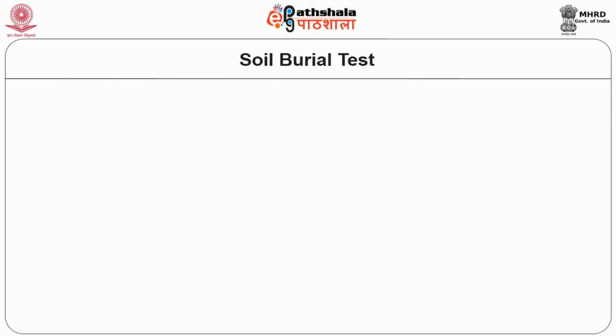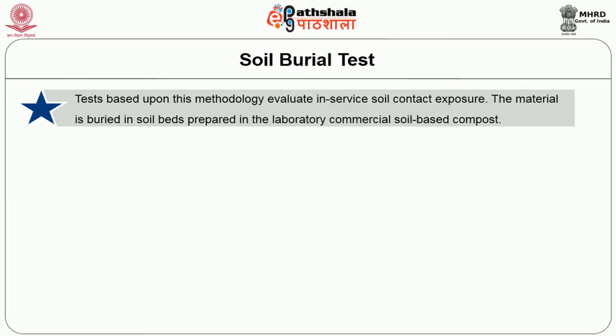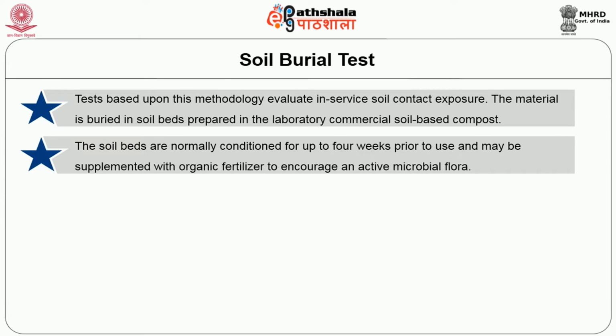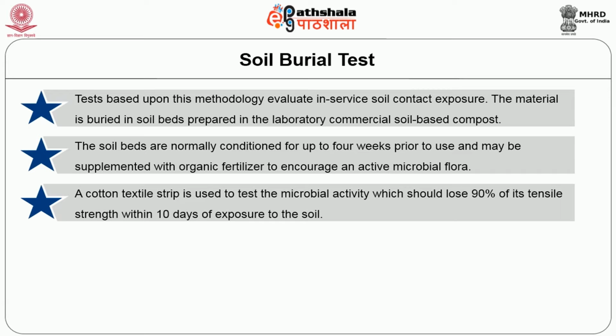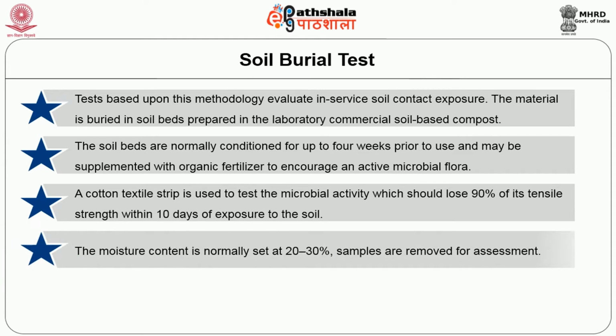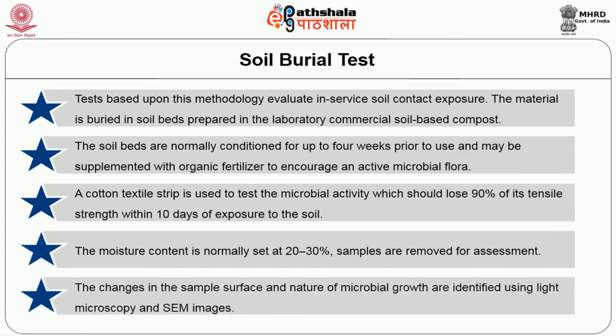Then finally, the soil burial test. The soil burial test is yet another test for assessing the biodegradability of the packaging material. This test evaluates in-service soil contact exposure. The material is buried in a soil bed prepared in the laboratory, commercial soil-based compost. The soil beds are normally conditioned for up to 4 weeks before use and may be supplemented with organic fertilizer to encourage an active microflora. A cotton textile strip is used to test the microbial activity, which should lose 90% of its tensile strength within 10 days of exposure to the soil. The moisture content is normally set around 20 to 30%. Samples are removed for assessment. The change in the sample surface and the nature of microbial growth are identified using light microscopy and SEM images.